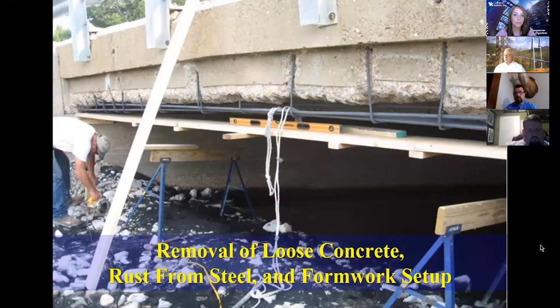And this gives us an idea on the steps in the repair stages that we go through. By the way, all the bridges I've shown so far, except one, have been repaired by the district crews, the bridge crews or maintenance crews. Now, in this bridge, the original concrete was down to this plank. And when we first looked at it, the concrete was down to where the rebars are. So in order to do the repair, we have to remove all the bad concrete. We cannot leave any of it in there. And then we have to clean via sandblasting or brushing, etc., the rebars to go back down to the bare steel, and then we protect the steel. And then we fill the concrete back to bring the beam back to its original shape.